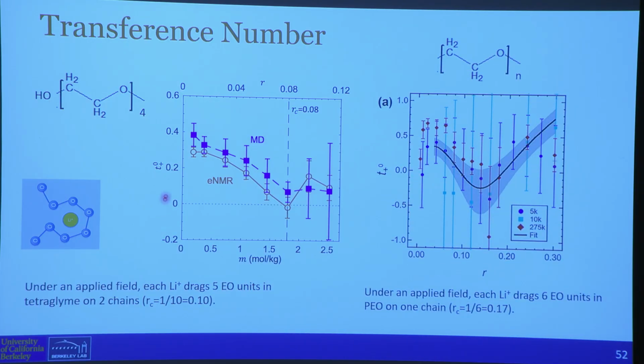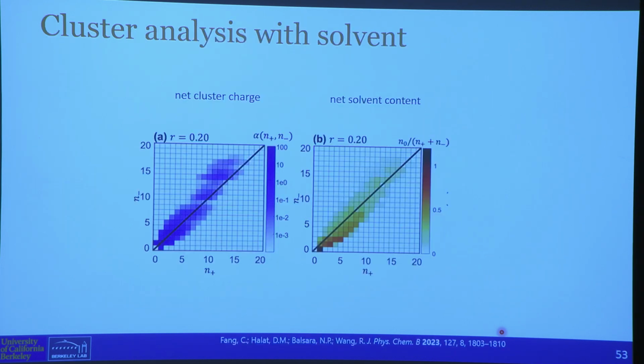I want to tell you that this shape is not that different from the shape we drew for PEO, except that the minimum is at 0.14. That's because we needed 2 molecules of tetraglyme, and we need only 1 molecule of PEO. If you do the math, you would get 0.17 for this minimum. And so all of this terrible performance of polymer electrolytes was coming from a limited transference.